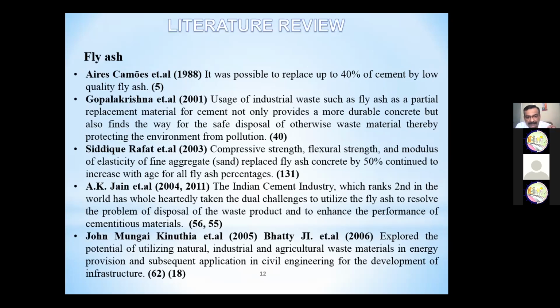So for fly ash, the cement replacement is around 50%, but it depends on the fly ash quality: whether it is class C or class F, or bottom ash or pond ash. So it depends. If the CaO is less than 20%, then it's class F because the plasticity is less. And if the CaO is greater than 20%, then it is class C, so plasticity is increased.